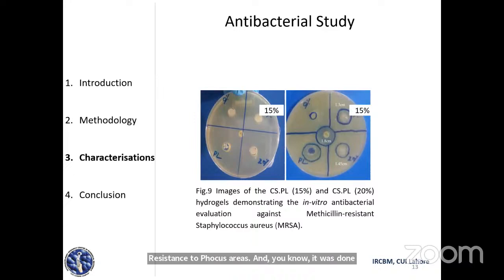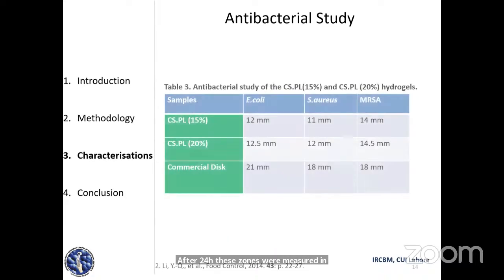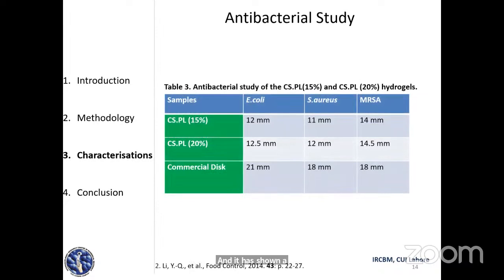All these bacterial strains were inoculated for 24 hours, and the optical density was set to 0.1, and these suspensions were prepared and streaked over these plates, and samples were placed. After 24 hours of placement of the sample, these zones were measured in mm, and it has shown good zones against all 3 bacteria.